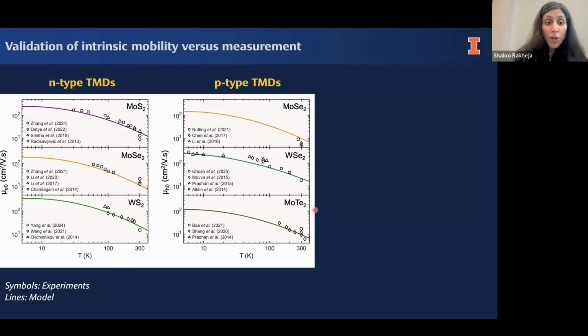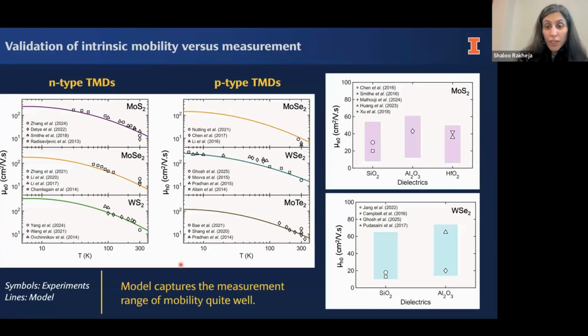So once we have our model, we try to validate the results against experimental measurements. So here we're looking at the measurement of the baseline mobility, which is evaluated at 0% strain. For N-type materials and P-type materials, the symbols over here are experimental samples, and the solid lines are the model predictions. And we can see that our model does a really good job at predicting a very broad class of materials across very broad temperature ranges, which is exciting.